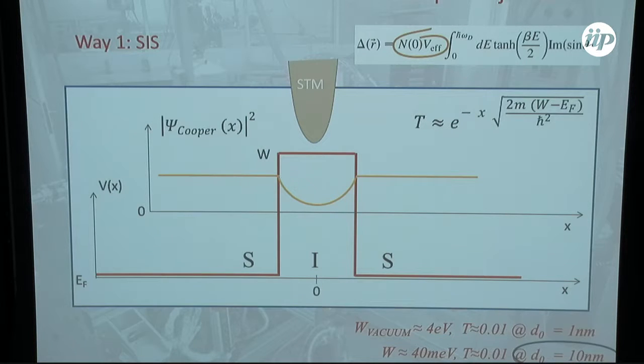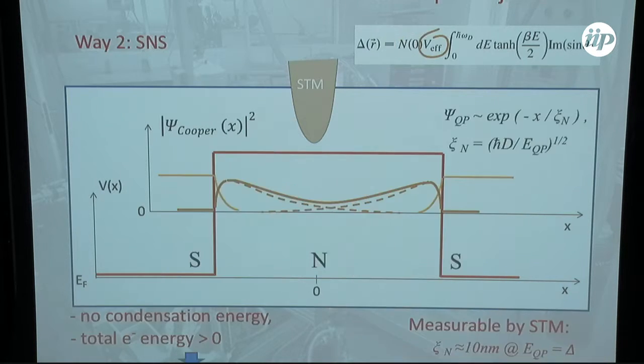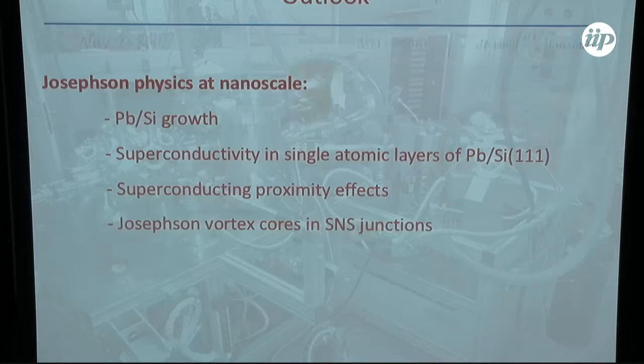But for the moment, we were not able to realize this. And there is another solution, which is to use SNS junctions. With SNS junctions, the Cooper pairs decay very rapidly at the interfaces, and they are converted into Andreev quasiparticles on both sides. These Andreev quasiparticles decay on a larger scale, and this scale is related to the energy of the quasiparticles and the diffusion coefficient. So in principle, in the case we studied, we can get something like 10 nanometers by this trick, and then you can study what happens inside.